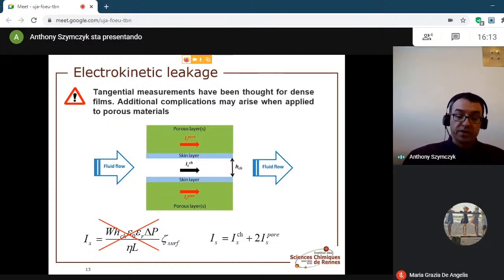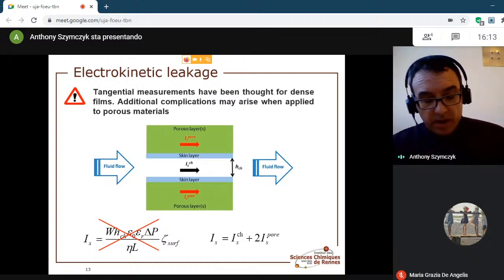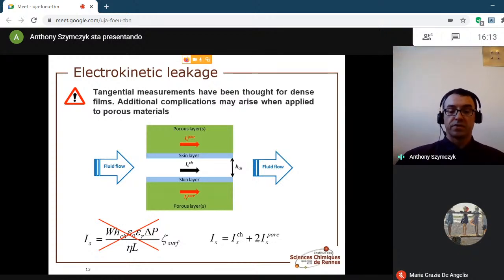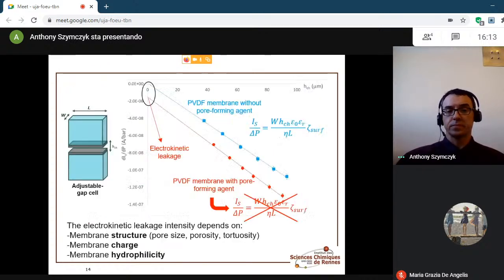This is the part of the signal we are interested in, but also within the matrix of each of the two samples. This parasitic contribution to the experimental signal, which I like to call electrokinetic leakage, has been largely overlooked in the literature, although, as we shall see now, it may lead to a relatively inaccurate determination of the zeta potential, or even to misleading conclusions about surface properties of membranes. Let's start by highlighting this electrokinetic leakage phenomenon.